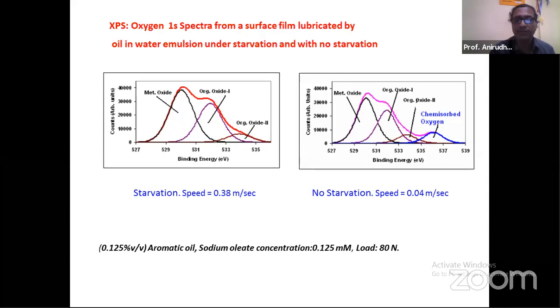If you see this, no starvation is at very low sliding speeds, which is almost 1 decade slower sliding speed as compared to the other one. It promotes the formation of a chemisorbed oxygen. Now, the presence of chemisorbed oxygen has been investigated by many investigators and researchers and found to be a very crucial element in the formation of lubricious tribofilms employing this kind of lubricants. So this is about XPS.